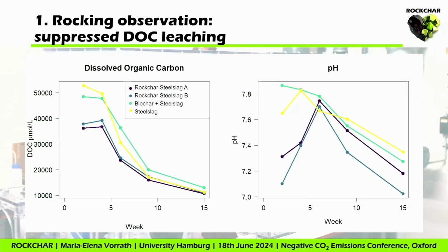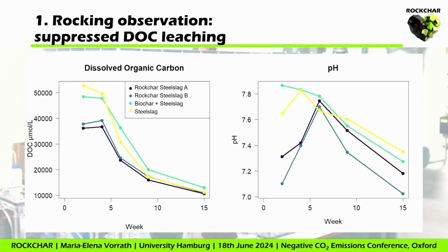So the first observation is we have a suppressed DOC leaching, and this is also referring to poster number 18. One problem is when we put biochar or enhanced weathering in soils, we increase the pH of the soil, and we can observe that more dissolved organic carbon is leaching out of the soil. The higher pH is triggering microorganisms to be more active in consuming more organic matter. So we are losing some organic carbon at the beginning, which you can clearly see here. We have a very high pH on the green and the yellow curve, and also a very high leaching of